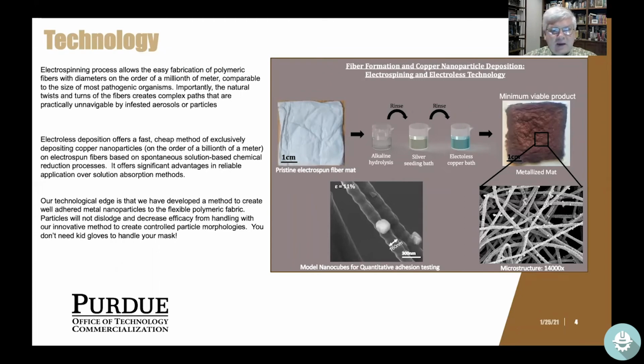The copper nanoparticles are stiffer, they're harder than the underlying polymer. And so if you think about a fabric, if you twist, turn, pull, stretch, bend, put around your mouth a fabric, you're going to be handling it. If those particles flake off, if they become loose, if the wearer breathes them in instead of having them stay on the mask, that's a potential problem. And so we need really well-adhered nanoparticles to this polymeric mask.